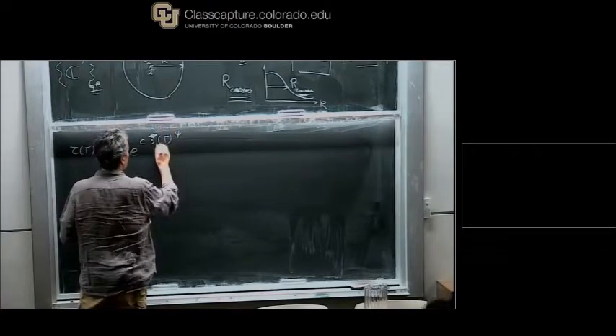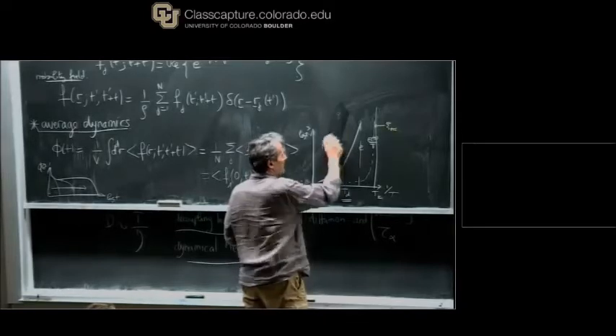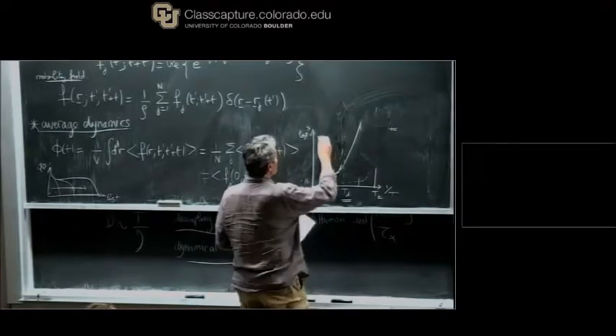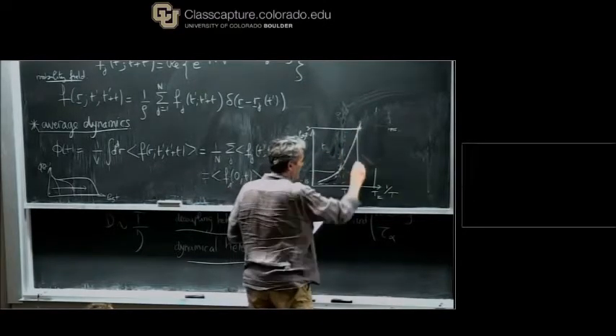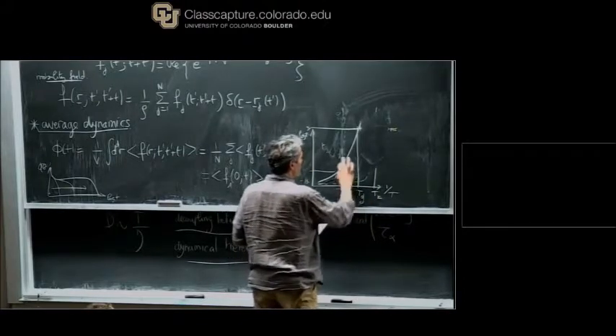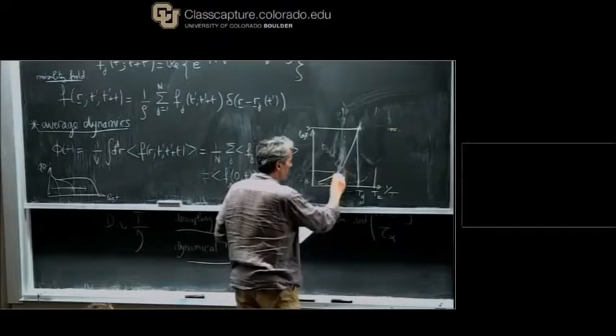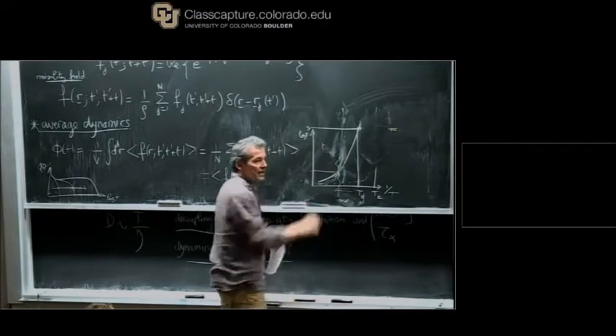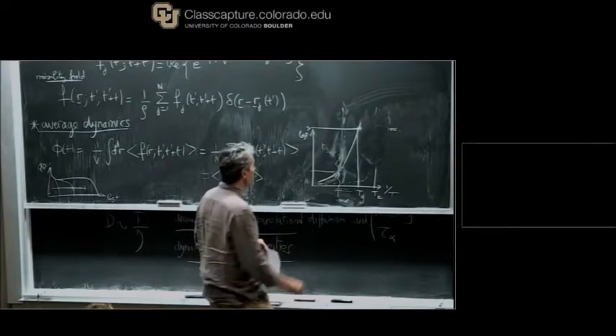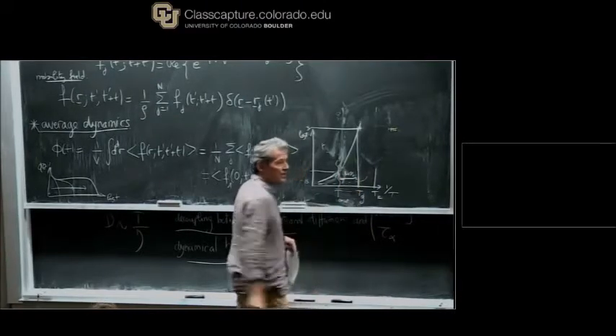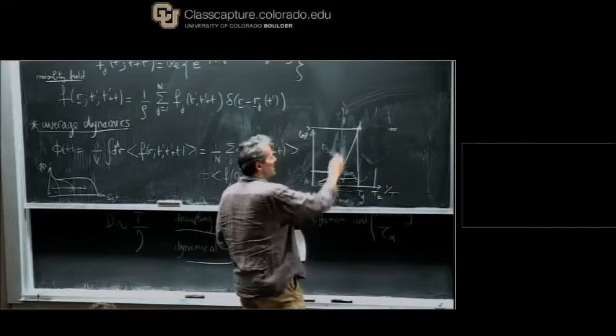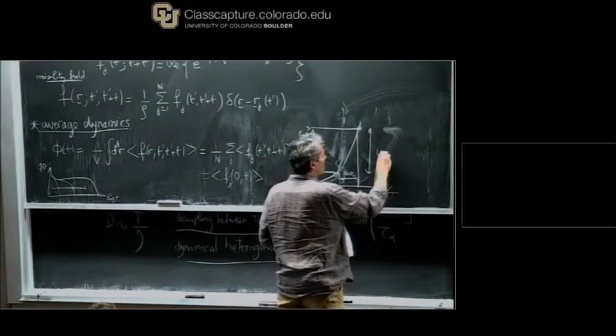So tau of T, say, has an activated dynamic scaling. Let's say it does this. And again, let's look at this. Now let's forget the mean field and the length scale. Okay. And let's look at this. So we said, all right, so this is TG here. And let's get rid of TD, which is, again, the mean field thing, and say, all right, but I have maybe some onset temperature at which things really begin to be super Arrhenius. And as I said, this is around 30% relative change. Okay, so here I have, say, between this and this, like 14 to 15 orders of magnitude.